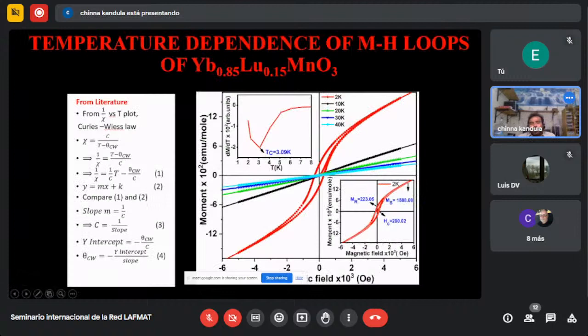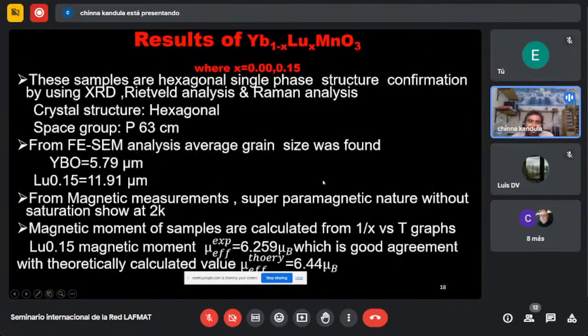You can see here. And I calculated the theoretical and experimentally effective magnetic moment of the sample. We found good agreement, 6.2 and 6.4, that means a very small difference of around 0.2. That means my sample is theoretically and experimentally verified, and it is good enough. These are the measurements I got.